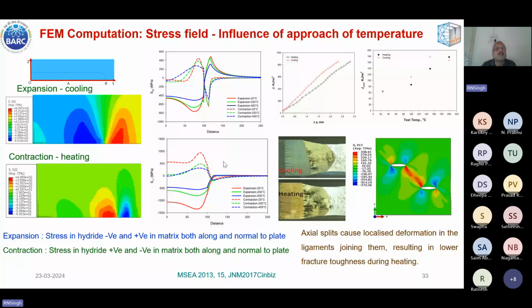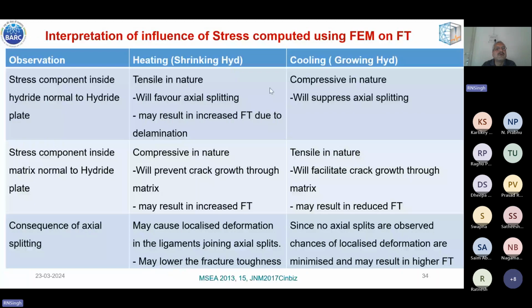So finally, some observations. A stress component inside hydride normal to hydride platelet during heating, that is shrinking, it is tensile in nature. So if a tensile stress is inside the hydride, it will favor axial splitting and may result in increased fracture toughness due to delamination. So in fact, we did observe larger axial splitting in case of heating case. However, during cooling, it is compressive in nature. So there is no axial splitting. So it will suppress axial splitting.